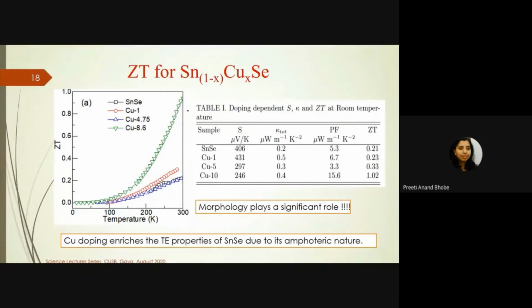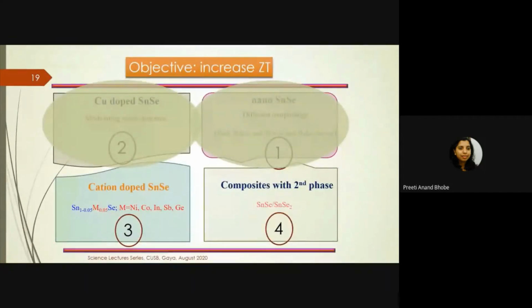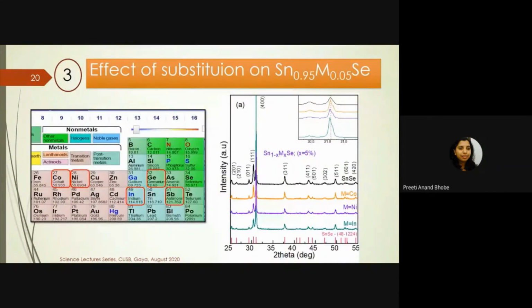So copper doping enriches the thermoelectric properties of SnSe due to its amphoteric nature and the microstructure it forms. Having done this, the obvious next question is, if copper is a good dopant, can I use other elements, like copper, and see whether my microstructure is improved and it helps me improve the ZT? With this aim, we look at the periodic table, and this time let me keep my concentration fixed. I know from my copper experience that beyond 5%, if I put some other foreign material in SnSe, it gives rise to an impurity peak. So let me stick to 5% and not cross it, but change different kinds of elements.